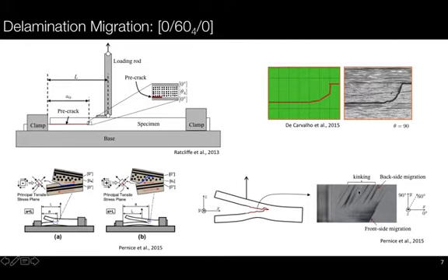You have many matrix cracks before the final migration, which shows that even though the stress state has satisfied the failure criteria for matrix cracks to appear, the energy state is not sufficient to promote the delamination from the lower to the higher interface.